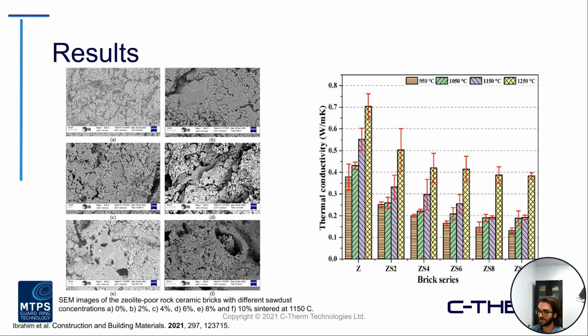From the results, again, we see some SEM imaging on the left there, but the story that we want to really take a look at here is that the varying sawdust concentration was noted to have a net decrease in the effective conductivity values, as seen on the right. But they're also firing these bricks, or sintering them, at different temperatures. So this is once the brick has been made, you heat it up, basically dry it, and then take that out and test as needed. There was also an influence that we can see quite notably of the sintering process on the effective thermal conductivity results as well.